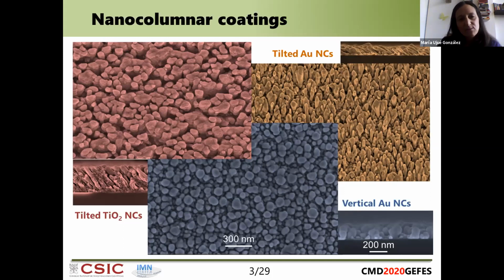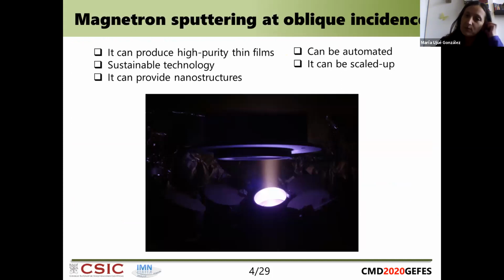So the first thing I would like to say is why we are using magnetron sputtering to fabricate samples. The reason is that this is a technique that is able to produce high purity films. It's a technology that in principle can be scaled up. It's used in industry to produce coatings, dielectric coatings for windows, for example, or for many other applications. And if you do this in a tilted deposition, you can obtain nanostructures. So it's a nice method to obtain nanostructures in a simple, affordable and cost-effective way.